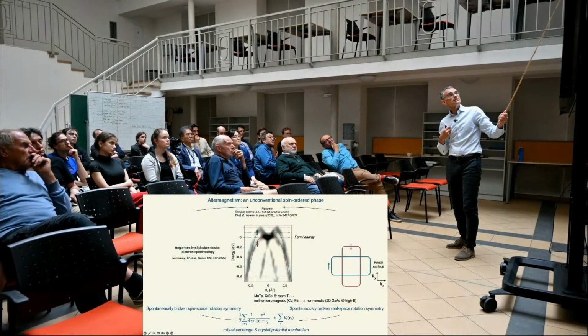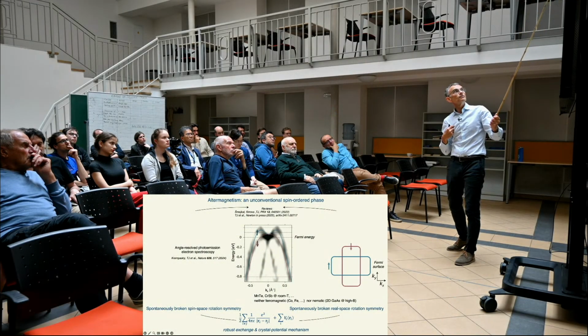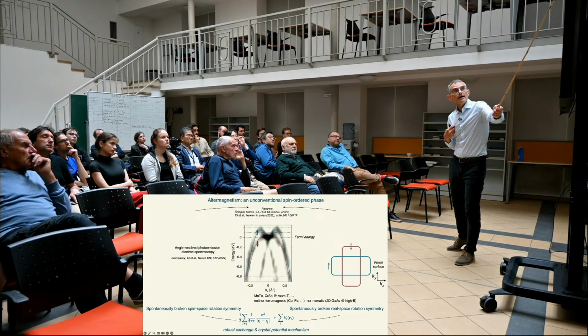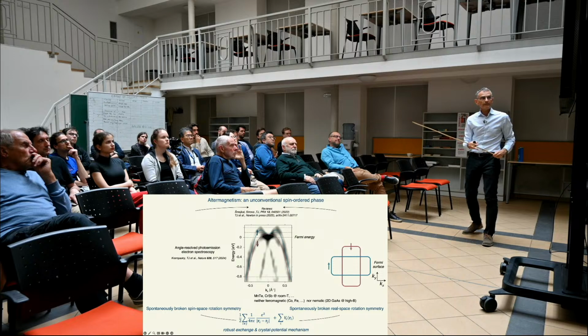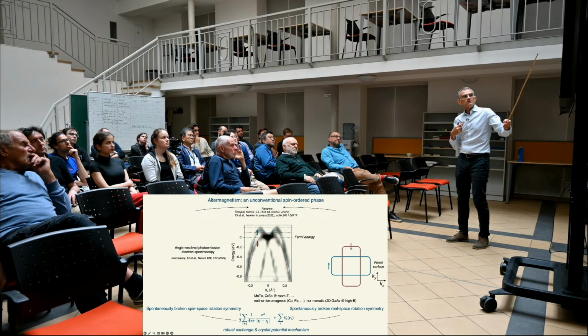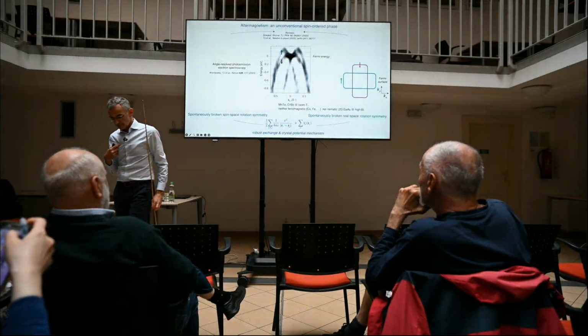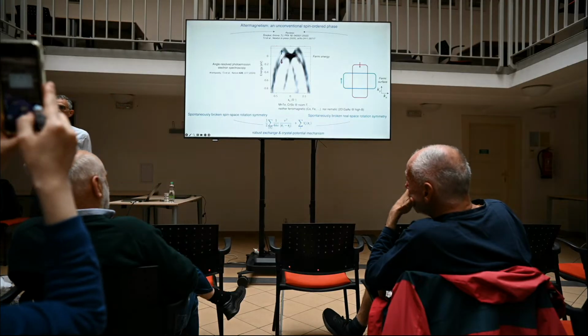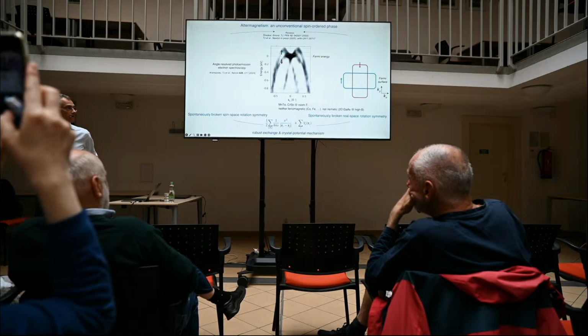So what you see here is the energy spectrum measured by angle-resolved photoemission spectroscopy. And this type of Fermi surface would correspond to this Fermi energy cut along the kx, going from blue, red, red, blue. It's exactly the same line, blue, red, red, blue. So these are different materials than the ferromagnetic ones, and certainly different materials than where we think we may have this nematic phase, which also means that the microscopic mechanism must be different. And it's also robust. That also tells you that it must be very different from the nematic one, which is very subtle and we don't even know if it exists.